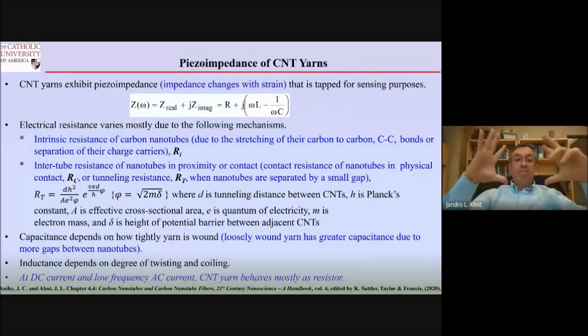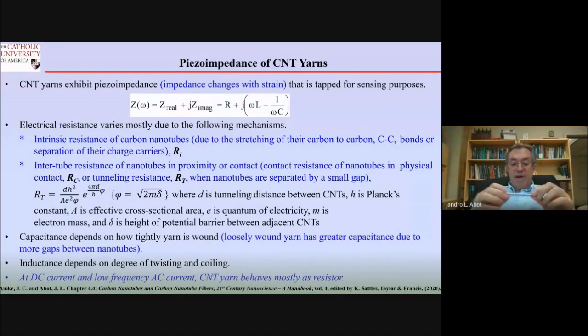So what is the physical mechanism behind sensing using carbon nanotube fibers? Well, it is something called piezoimpedance. I'm not sure if you can see my hands here, but imagine you have a fiber, right? Imagine this as a CNT fiber. If I pull the fiber and measure the electrical resistance, I can use 2 probe or 4 probe, the electrical resistance will change. So I can correlate the change in electrical resistance versus the strain, the unit deformation. Sorry, I switched to English. If you measure the electrical resistance and correlate it with the strain, you have a piezoresistive behavior.